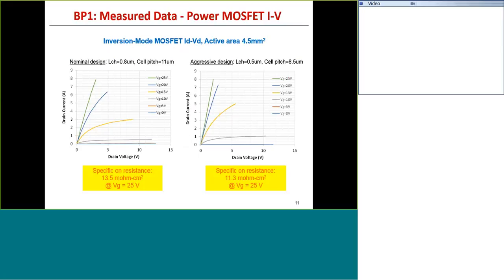So here's the output characteristics at small voltages to show you the output characteristics as well as the on resistance. The inversion mode MOSFETs were designed with two channel lengths, more than two, but these two are shown here, one with a channel length of 0.8 micron and the other with a channel length of 0.5 micron, and both were fully functional. The RDS(on) is reduced by reducing the channel length because the channel contributes a large fraction of the total on resistance. So by going from 0.8 to 0.5 microns, the specific on resistance was reduced from 13.5 to 11.3.